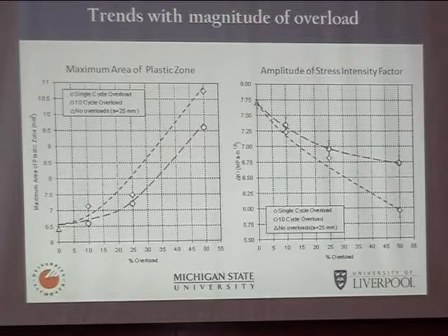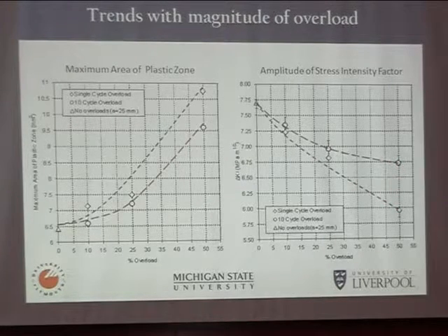And so with the 10 cycles of overload, the crack's actually been accelerated through the enlarged plastic zone, so what we're measuring is sort of slightly post-event plastic zone size. And the same thing, I think, explains what's happening over here. The circles here are the 10 cycles of overload, and so the lowering of the delta K appears to be less than with the single overload. So in fact it probably creeps back up here during the 9 cycles following the first one.